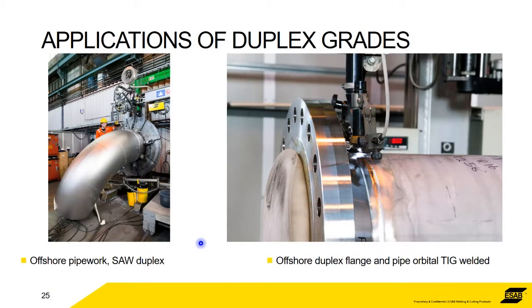Obviously, offshore, we're talking high corrosion offshore applications. There's a very nice example of submerged arc. You can submerged arc these duplexes, that's not a problem. And we've got another example here with a flange, which has been done by Orbital TIG. So again, the application is for offshore. They're using duplexes or even super duplexes in some of the more corrosive environments for the pipe work.